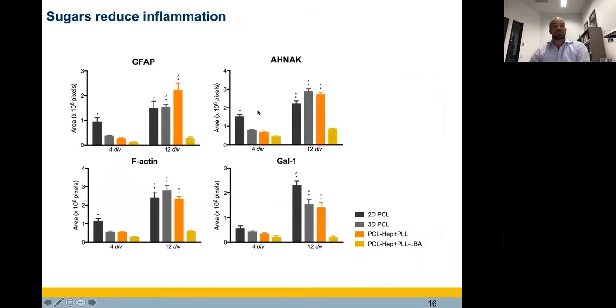So I won't go into too much biology here, but what I did want to show, these are all just markers of sort of the reactivity of an astrocyte. But the important thing here is when we culture them in 2D, like I said, they're always reactive. When we cultured them in 3D, in the gray here and all the other groups, you can see we've reduced that level of reactivity. Now, what we did is we wanted to present that sugar moiety, the galactose that I was talking about earlier, on the surfaces of this three-dimensional morphology, and see what happened. Because what we saw when we had this sort of 3D morphology is that after 4 days of in vitro culture, yes, it's suppressed. But if we go to 12 days of in vitro culture, you can see they're inflammatory again. Okay, so we're not getting that sustained suppression of this reactive state.